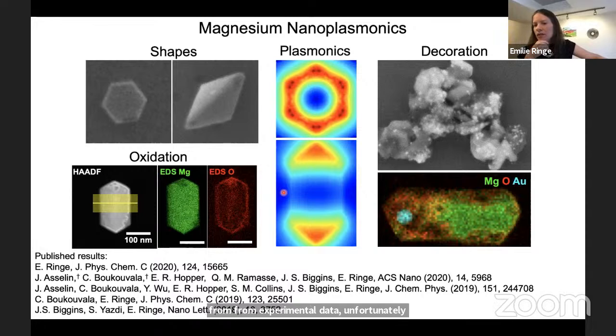Unfortunately, we really don't have a good way to control this oxide layer. Deliberately trying to oxidize the particles is really quite uncontrolled. And so we don't have kinetic data based on that. I would definitely expect that you would get basically slower kinetics with thicker oxide, but I don't have data to show that. That's a really good question, and the day we manage to control the oxide layer, we're definitely trying that. Thank you.